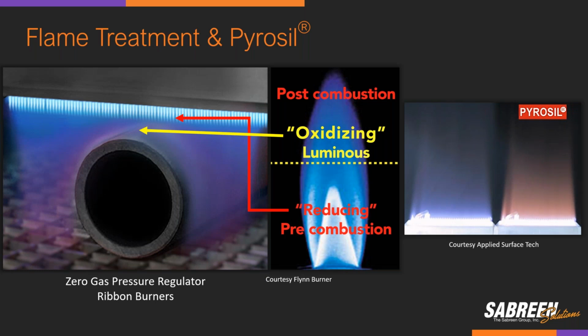And then when you extend farther out, you get into the post-combustion zone, which really has negligible pretreatment effects. So to properly use the flame treatment, it's absolutely critical to have each of these zones properly set up. And I can't stress enough that before you buy any equipment, make sure that it has a zero gas pressure regulator, and also at least analyze whether or not you're using ribbon burners or drilled port. Sabreen has found that ribbon burners oftentimes provide the best result.